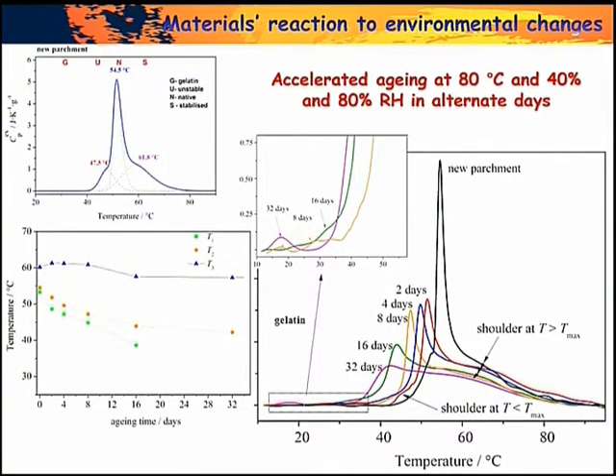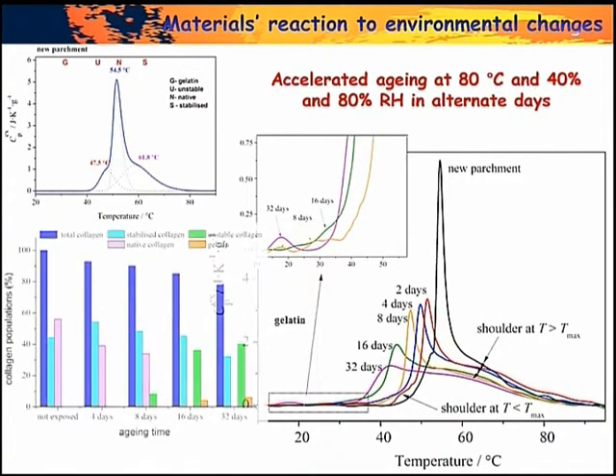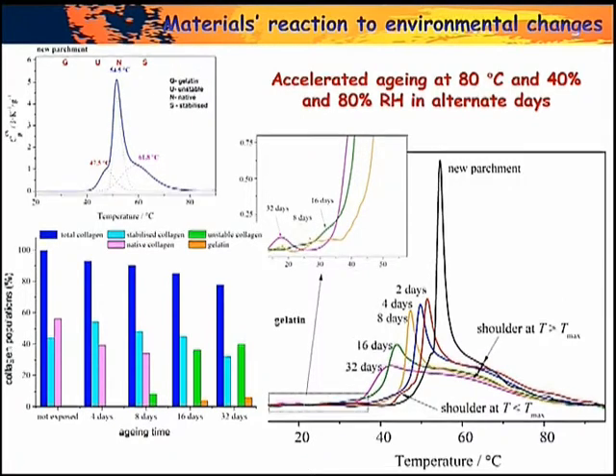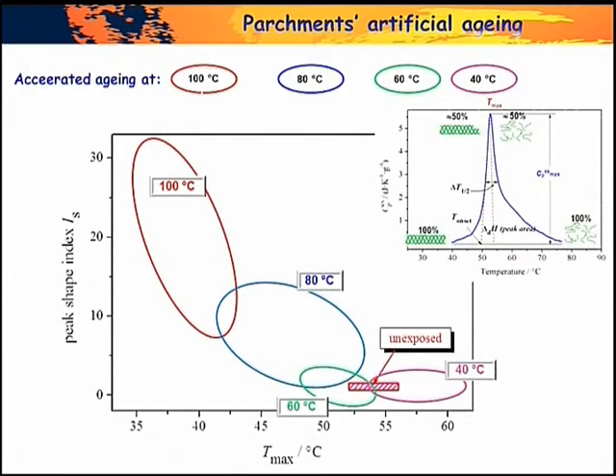If we quantify this collagen population, we see that the native collagen in pink decreases, while the unstable green and gelatin fractions increase. Also, there is a decrease of the total collagen population, so a part of this collagen converts into a non-reactive form, so we can no longer detect this kind of collagen in a very high deterioration state by this technique.